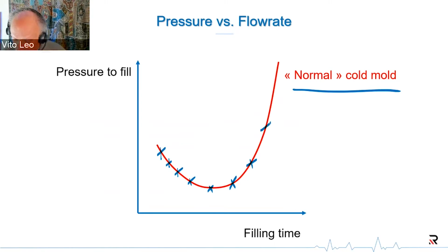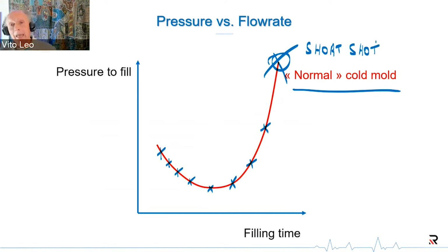And it goes up so dramatically that you reach a point where you produce a short shot. So there's no way to fill your cavity, and that's why there is a concept of minimum filling rate, and a concept of optimum filling time, which you could identify as being, say, the minimum of this curve.